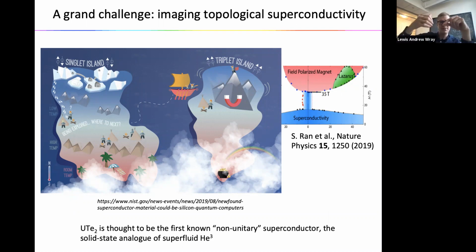The symmetry is stabilized by spin orbit coupling, which tries to give you a superposition of the spin up triplet and the spin down triplet as a coherent superposition as the ground state. But when the superfluid density becomes high enough, you then get a magnetic transition within the superfluid. So that's observed. It's like helium, as you said, like helium-3.